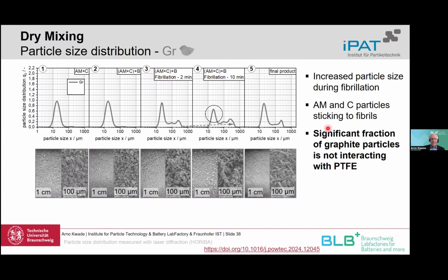And then we have a final homogenization at lower temperatures for the final powder properties. And what happens regarding the size distribution, for example, here the graphite, you see at the beginning without PTFE, there's not changing a lot. It shouldn't be that there's a change, but after adding the PTFE, fibrils formed, and these formed fibrils then also form agglomerates or granulates inside the mixture. This is seen here. And with increasing fibrillation, there's, let's say, an increase in the granulation size and also amount.